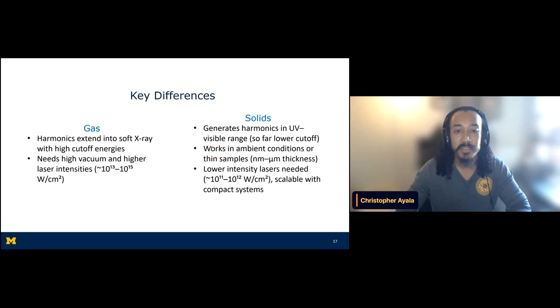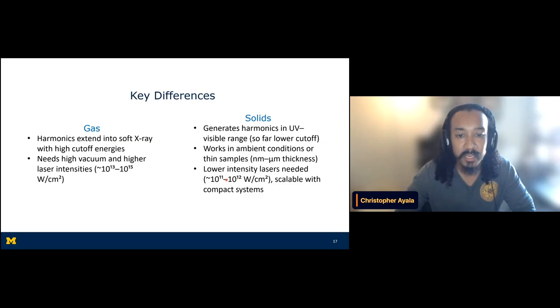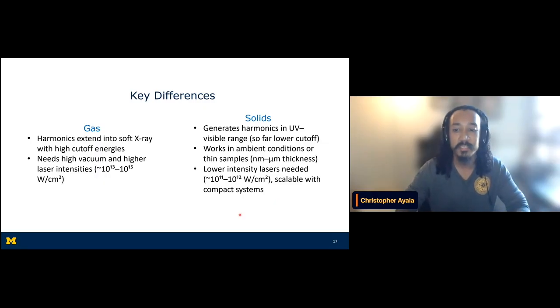For example, solids can generate harmonics up into the UV range, which is lower than the X-ray range, but we're able to do so within ambient conditions, and we're able to change and determine different material growth and material observations with solid harmonic generation. The other thing to note is that the laser intensities are about 2 to 3 orders of magnitude less, and that allows you to scale and have compact systems relative to gas phase harmonics.